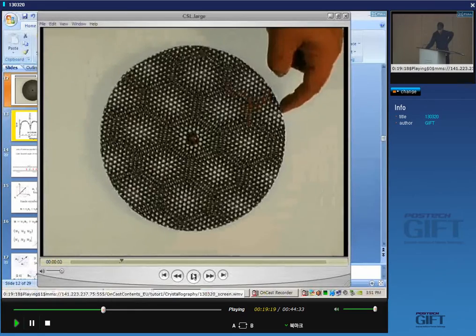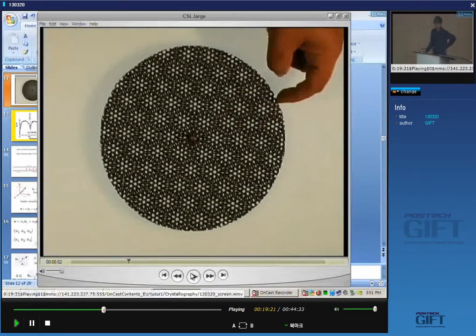That's my finger. Okay. So this is just one particular value of theta. And you can see that at certain points, the lattice points of the two crystals are exactly in the same place, right? So there's perfect matching between the two crystals at certain points here. And not only that, but those coincidence points, we call them coincidence points because they coincide exactly, yeah? They form a pattern which is called a coincidence site lattice.